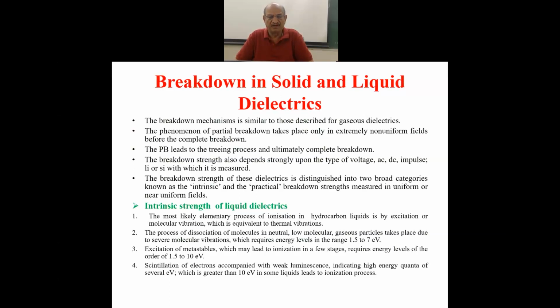So it is very difficult to standardize or say this is the breakdown strength of this dielectric, because the condition of the dielectric and the measurement conditions under which it has been measured would determine the breakdown strength. So there is no one value of breakdown strength in case of solid dielectrics. But the breakdown mechanism is similar to those described in gaseous dielectrics. The phenomenon of partial breakdown takes place only in extremely non-uniform fields, as we have learned, before the complete breakdown. The partial breakdown leads to the treeing process, and the development of the treeing process would also determine the breakdown strength, because the treeing process ultimately does lead to the complete breakdown.